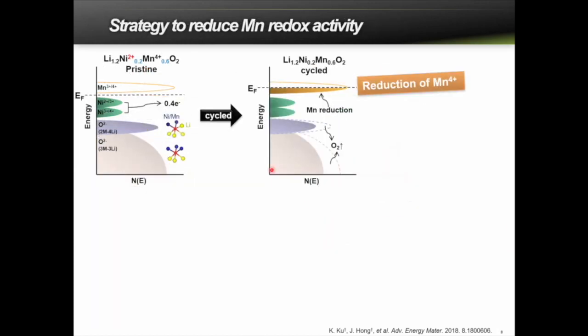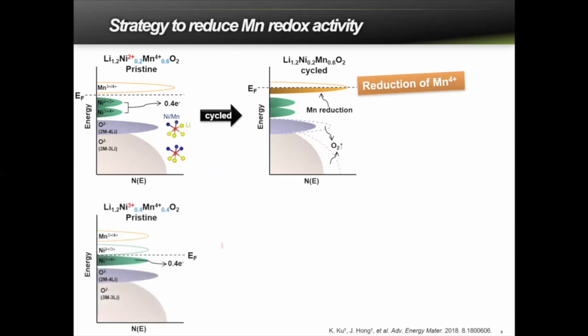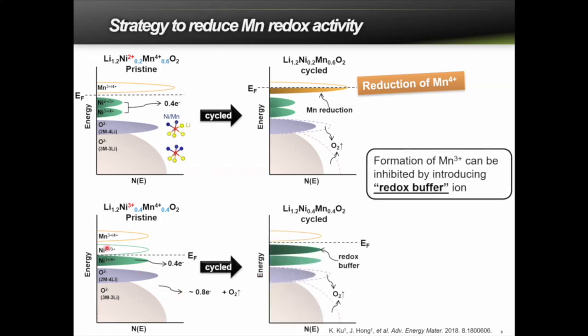So if this is the case, we thought that we can simply detour this problem by introducing an additional empty state of a high redox transition metal in the density of states. For example, if we increase the nickel content from 0.2 to about 0.4 like this, then the overall oxidation state of nickel becomes 3+, and it will generate the empty state of nickel 2+ just below the manganese states. Even when there is a loss of oxygen during the charge, some of the unoccupied levels from nickel are going to be occupied due to the alignment of states, and then it will prevent the manganese redox participation. And we call this a redox buffer.